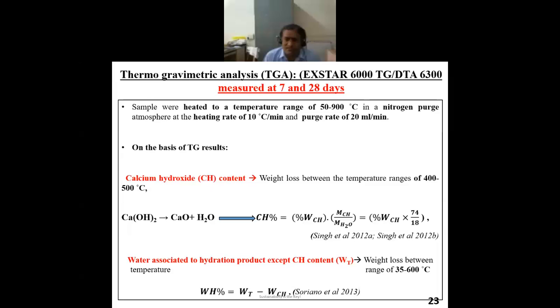cement paste with the help of thermogravimetric analysis, or thermogravimetric analyzer. This is the standard: samples are heated with a temperature range of 50 to 900 centigrade in a nitrogen atmosphere at a heating rate of 10 degrees centigrade per minute, and a purge rate of 20 milliliter per minute. That is the equipment requirement.